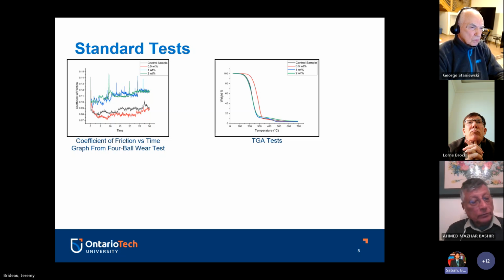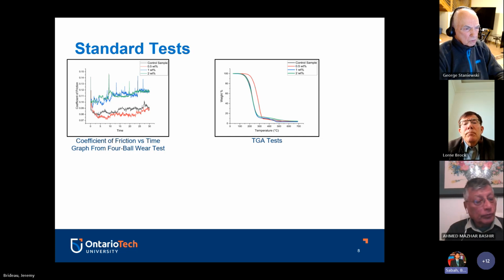And the reason why the 1% and 2% are also in line with the control sample is because once you get too much graphene, the chances for particle agglomeration is a lot higher, meaning that when it creates this lattice, it's going to have graphene particles in the mix there, causing multiple clumps, and that just makes it a lot easier for it to degrade or disintegrate at those temperatures.